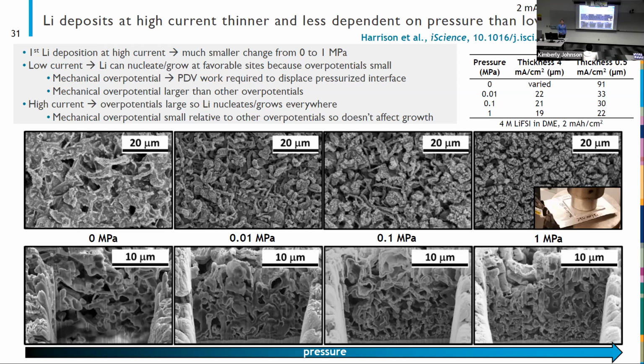And we think that what's happening is that at low current density, lithium can nucleate and grow at very favorable sites on the surface. We don't have transport limitations or kinetic limitations. So if we're driving at a very low current density, we can have these sites on the surface, defect sites for example, where lithium would prefer to grow, and it'll nucleate there and then just continue growing there because we can move lithium ions as easily as we want. We can move them all over and we don't have to plate in non-favorable regions because we have enough time, since this is a slow current density, to move the lithium ions to those favorable sites.